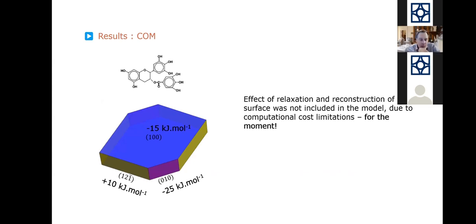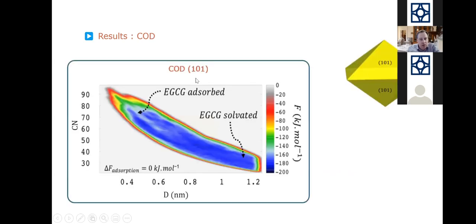With molecular dynamics, we did this for the different surfaces that you see here. We have the catechine adsorption on the 1,0,0 surface, 0,1,0, and the 1,2,-1, and we see that there are some favorable adsorption surfaces or orientations and unfavorable ones. This is what has been calculated. How did we do that? We did that with metadynamics. We use as variables to follow the parameters that we defined before, the distance here on the x-axis and the coordination number. In order to have adsorption, we have to be in this area, small distance, high coordination number. If you are solvated, then you are far away from the surface, and you have a low coordination number. So you go from solvated to adsorbed. Then we can calculate the free energy at every point, which is a part of the potential energy surface.